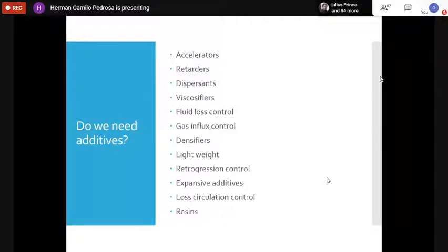So we have the accelerators. Sometimes we have a cementing operation that won't take so long. For example, it can take just half an hour of operation. So if we have a cement that will become solid after many hours, after 10 hours, that will be a problem, because we will be wasting time just waiting for that to happen. And as I'm pretty sure you all know, an hour on the rig is very expensive. And now it's even more dangerous to just waste money waiting for something to happen. So this is the reason why we use accelerators. If we have a cement that sets in 10 hours, we can put in some accelerators and have it set in 2 hours or in 1 hour. So it depends on our placement time.